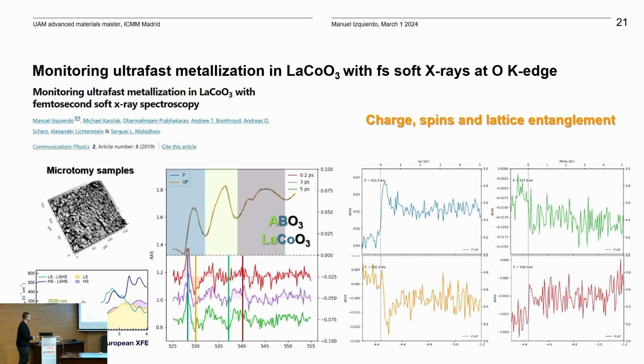The second thing that we wanted to do is, if you have a perovskite ABO3 and then you look at the oxygen K edge, you are going to distinguish three different areas. The first part is the result of the hybridization of oxygen with the B material, which in this case is cobalt, the 3D material. The intermediate region is the hybridization of oxygen with the A element, in this case lanthanum, and the last region in this particular case is the 4sp band, and this is related to bond length and distances.